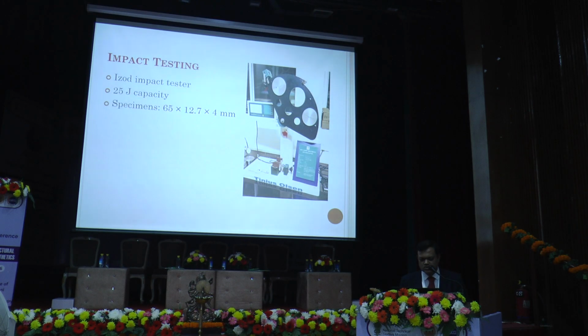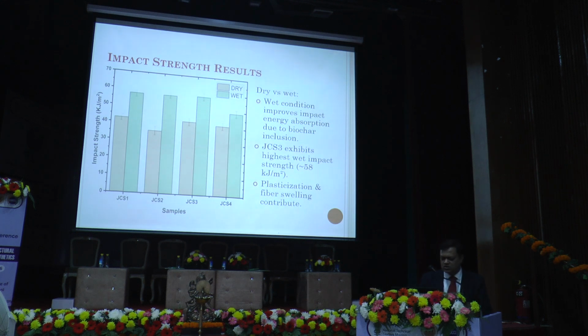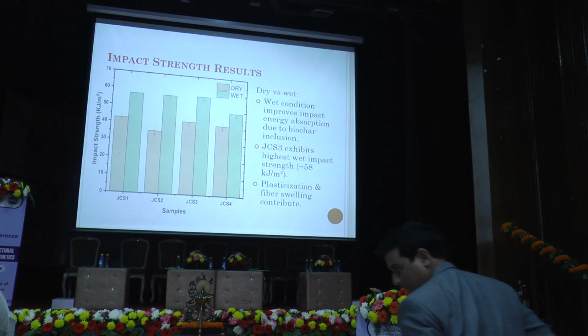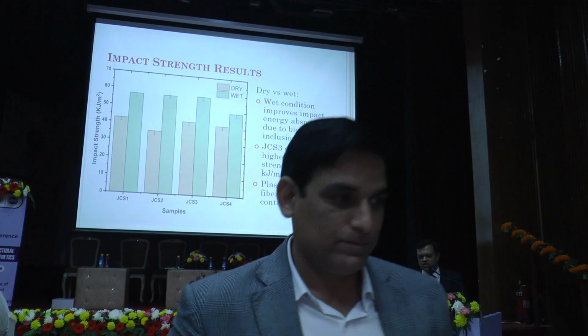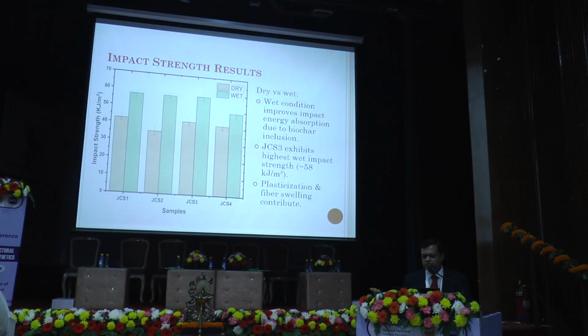The impact testing was done in an IZOD impact tester with 25 joule capacity, and you can see the results. The dry versus wet results were compared, and it was seen that the wet condition improves the impact energy absorption due to biochar inclusion, which was very good and encouraging. The sample JCS3 exhibits the highest wet impact strength of almost 58 kJ per meter square.